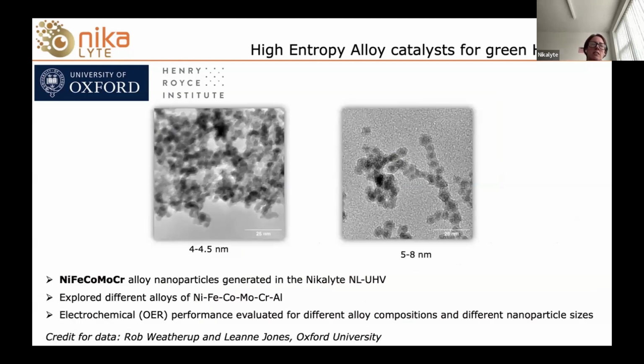So the materials generated by Rob's group, they looked at nickel, iron, cobalt, moly, chromium alloys, and these were generated with different sizes. So we've got TEM images of 2 different size nanoparticles, and you can see they've lined up in these nice columnar structures because they are magnetic materials to some extent. And the team looked at different compositions of alloys. So they looked at mixing aluminium or chromium in with the high entropy alloys, and then performed some electrochemical testing of these materials with different alloy compositions and different nanoparticle sizes.